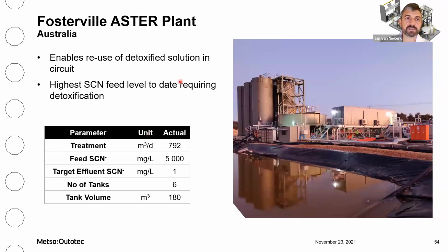And the latest aster plant is the Fosterville plant in Australia. Here the aster really enables reuse of the detoxified solution, again in the BIOX circuit, and they treat the highest thiocyanate feed levels to date. They see up to 5,000 ppm thiocyanate in their feed, and the target is to achieve below 1 ppm. This plant was commissioned earlier this year, so we're still gathering the operating data, but so far it is operating very well.